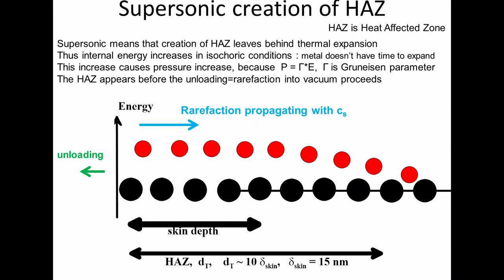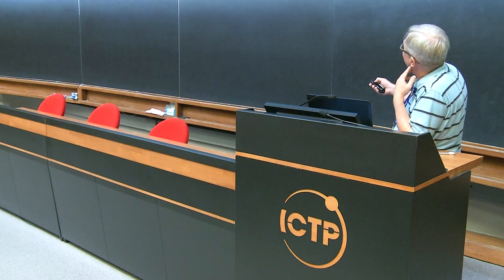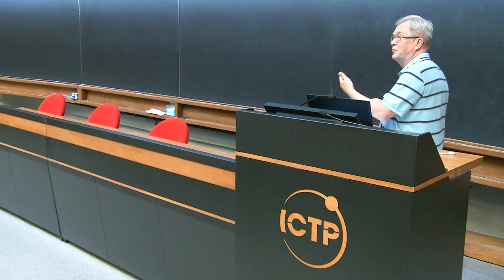Supersonically means that rarefaction propagation, and we heat the system. Therefore, we raise pressure just because we raise energy and we don't have time to expand, to release this energy, to release this pressure, to unload matter. We don't have time because it is supersonic. Therefore, pressure rises and matter begins to unload to the vacuum side, and the rarefaction begins to propagate into the bulk.